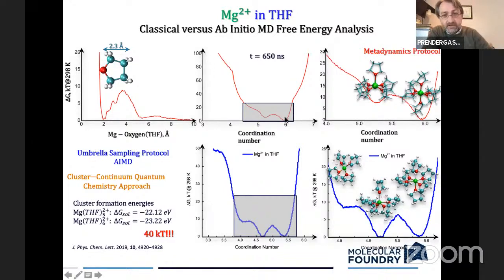Now that we examine the free energy, we see it makes sense. They are both local minima in the overall free energy landscape. And so, yes, you should expect a mixed population of both, with their relative populations defined by the Boltzmann factor based on this free energy difference here, which in the classical simulations was about 7 kT.